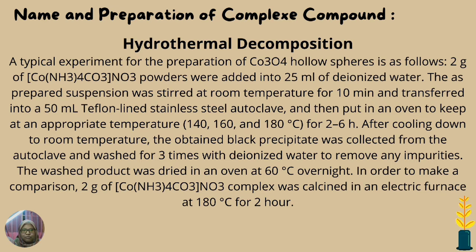The prepared suspension was stirred at room temperature for 10 minutes and transferred into the 50 ml Teflon-lined stainless steel autoclave and then put into an oven to keep at an appropriate temperature, which is 140, 160, and 180 Celsius for 2 to 6 hours.